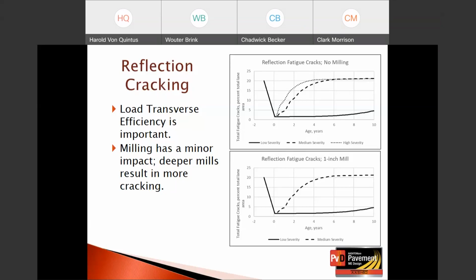The deeper mills, obviously going from 1-inch, 2-inch, 3-inch, depending on the thickness of the existing asphalt layers, the deeper the mills do result in more cracking. Or I think that the deeper mill should be less cracking. That's an error in this slide, I'll have to correct. The deeper mills should result in less cracking.